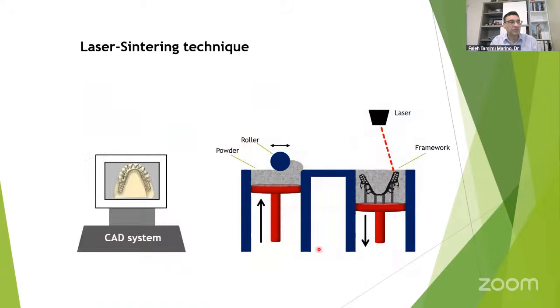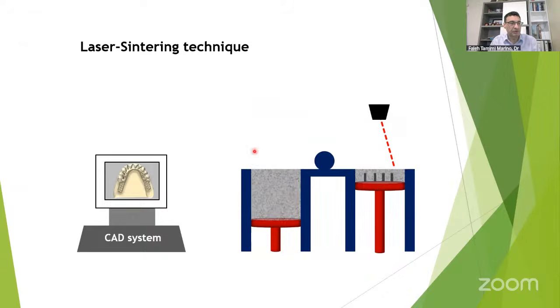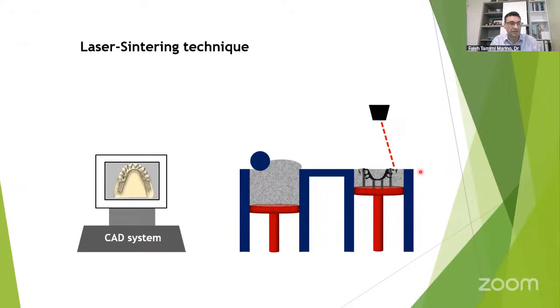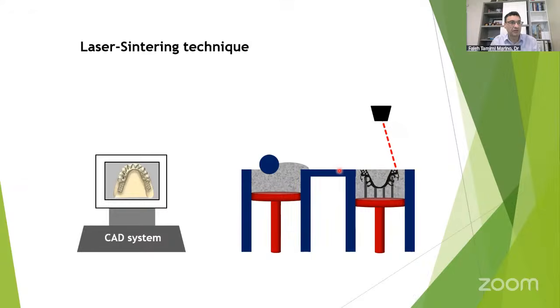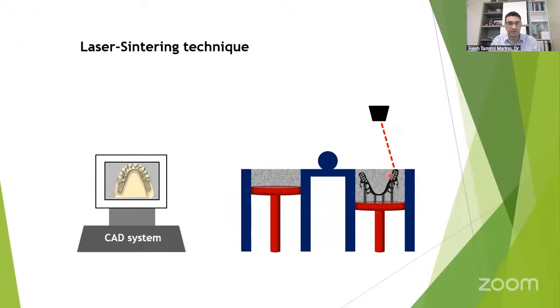Okay, so if you have a machine that can create these layers step by step, so for example, with a roller, you can add a layer of powder, and then you have a laser beam hitting the powder in certain areas, then you can add another layer, and you have the laser hitting the powder in different areas. So that way, step by step, within a piston of powder, you can build a framework of a partial denture. Okay, so this is how it works.